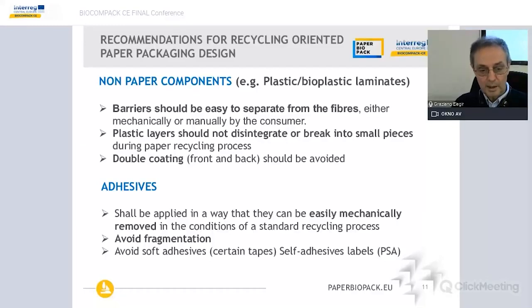With respect to the adhesive, instead, it's not so easy to give some general recommendation, but for sure adhesives have to be applied in a way that they can be easily mechanically removed in the conditions of the standard paper recycling process. And actually, this is important not only for the standard recycling process, but also for those mills that use very difficult multi-material, because adhesion is really an issue for all the different standard recycling processes that we have in Europe. Also, for adhesive, it is important to avoid fragmentation.